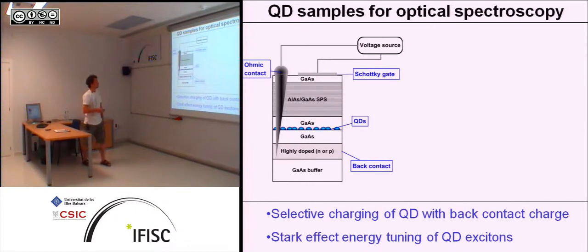Okay, so what do you now do with such an atom-like system in the solid state? Well, you can do what you do so well with semiconductor material science: you grow some functional structure around it. If we start from the bottom, this is the gallium arsenide substrate I was showing you before, where you grow the indium gallium arsenide on top of it. The next step is to grow a highly doped region, which can be negatively or positively doped. You cap that again with gallium arsenide, then you grow the indium arsenide quantum dots on that with another capping layer of gallium arsenide, and then you grow something called a superlattice, which is the electronic equivalent of a Bragg mirror, basically.